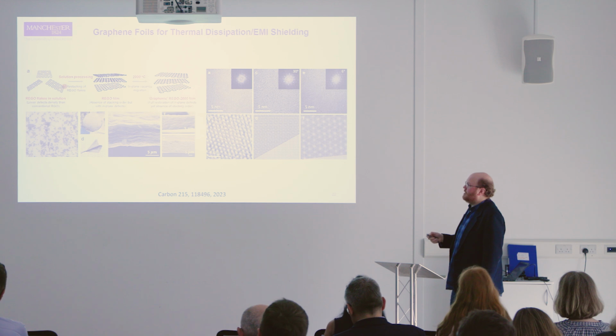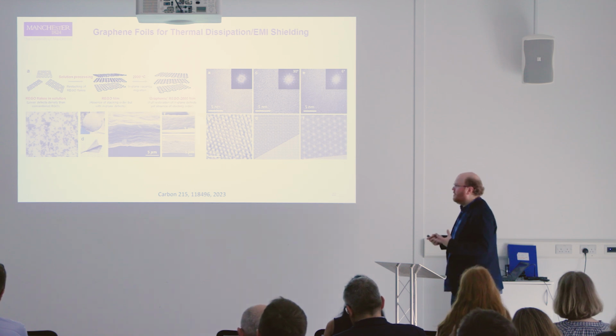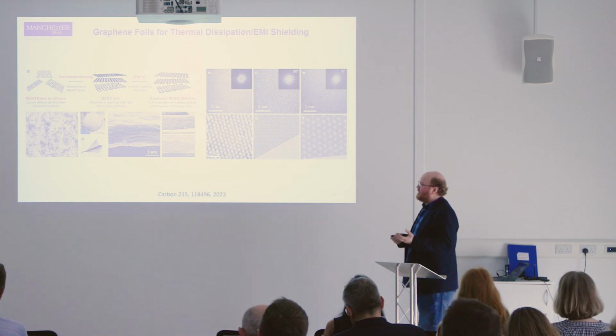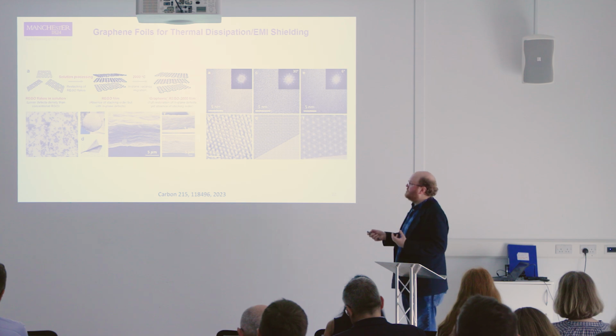So in this work we were taking some electrochemically exfoliated graphene oxide, and we were actually getting rid of those oxygen molecules. And so you've got essentially a reasonably defective graphene layer. You stack them together, it looks something like this. These are the individual flakes. These are stacked as a thin film or as a coating. And this is the sort of laminar structure of these layers.